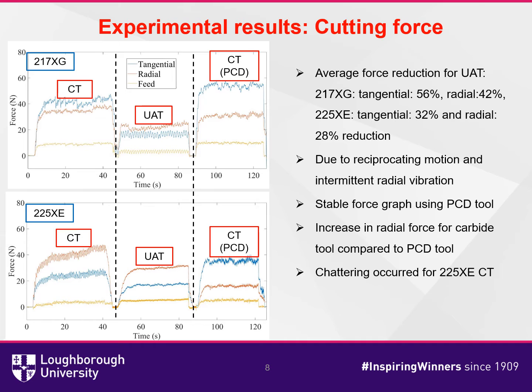For both workpieces, the force reduction was due to tool-chip separation and intermittent radial vibration. Feed force was only reduced for 217xg due to dampened vibration caused by hard silicon carbide particles for 225XE. The forces were much more stable for both CTs using PCD tools compared to carbide tools, but tangential forces were higher due to more impact acting on hard PCD tools, whereas soft carbide tools allow the particles to be embedded on the tool surface.